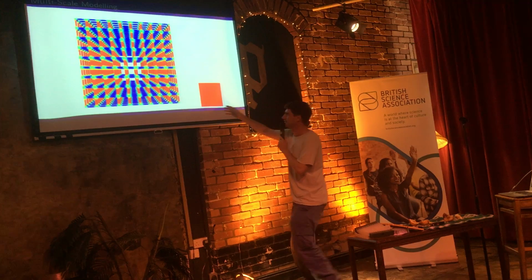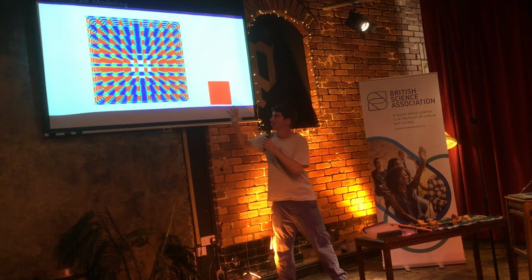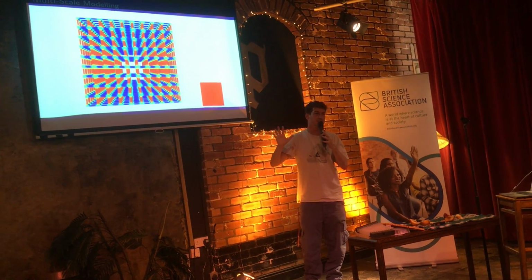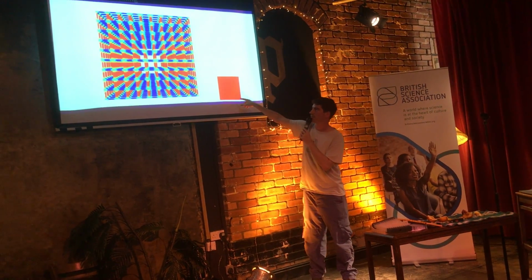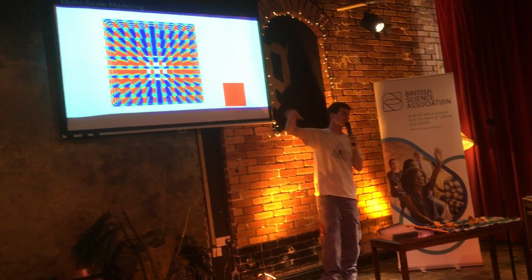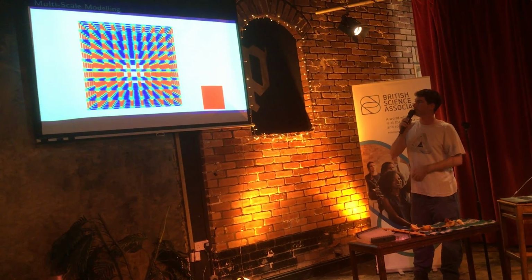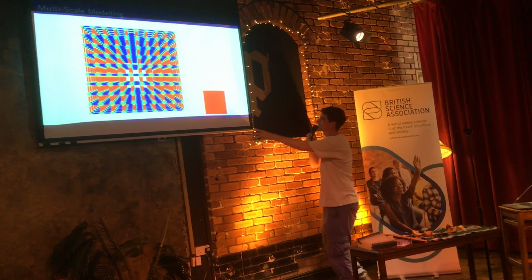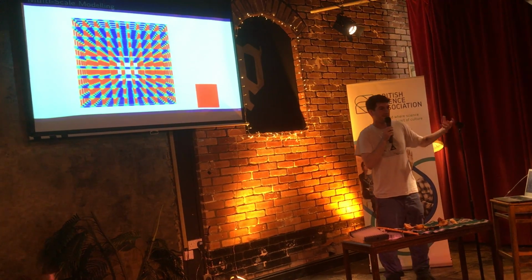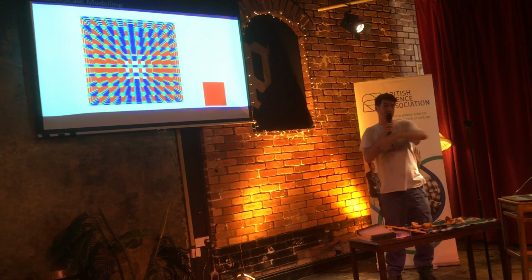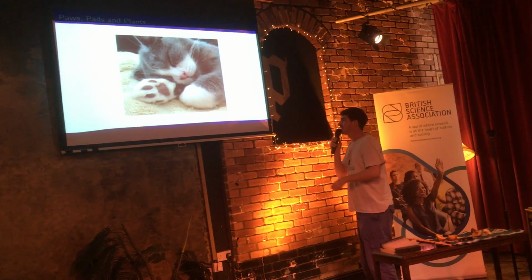So here we have like the red is like a high stress, so we're pulling this structure up, and the blue is a low stress, so it's not really moving laterally that much. It's all in this direction. And our multi-scale model gives us the same average stress over the structure, but it's much easier to calculate. And this is really good in terms of, it makes complicated things more accessible to engineers that can then take a real material and fit the data of that material to a model that is then easy to calculate. So, we've got a cat picture.